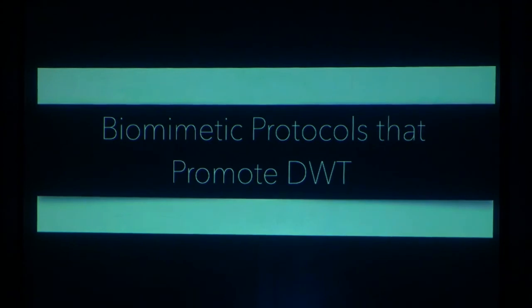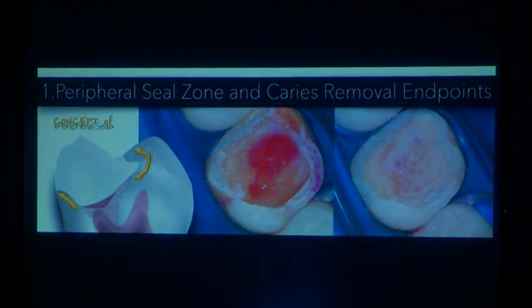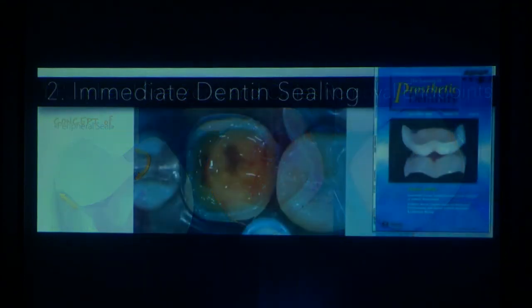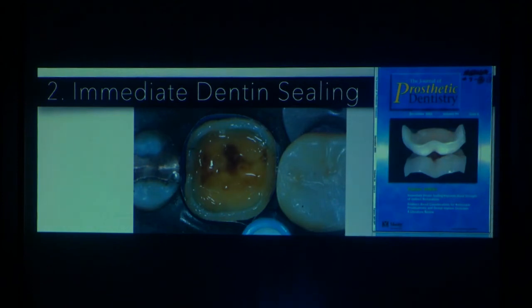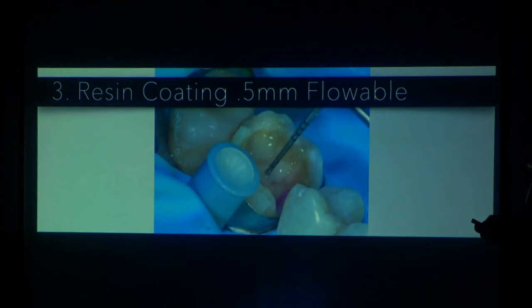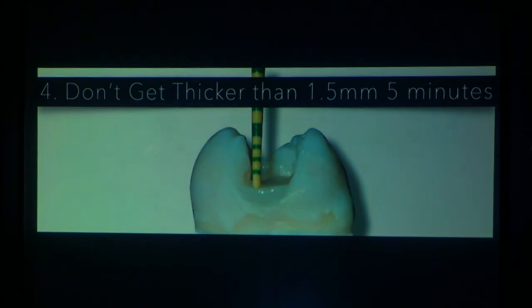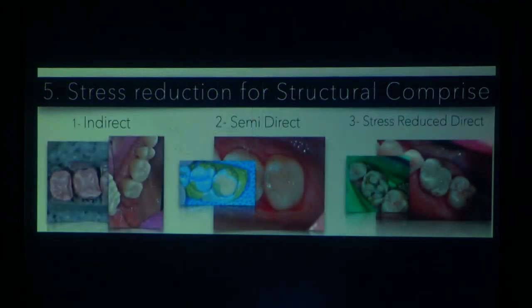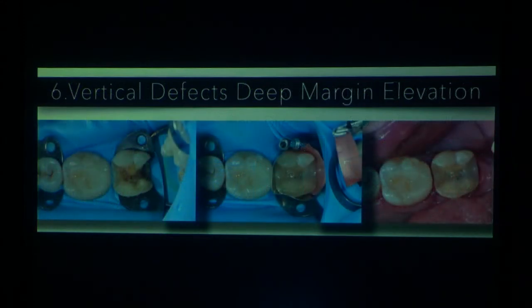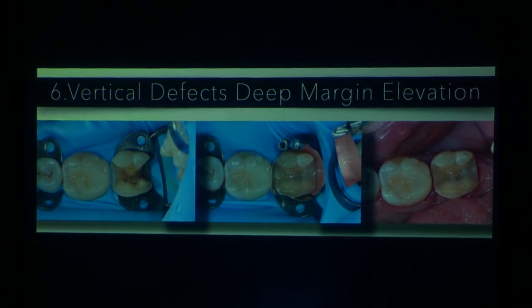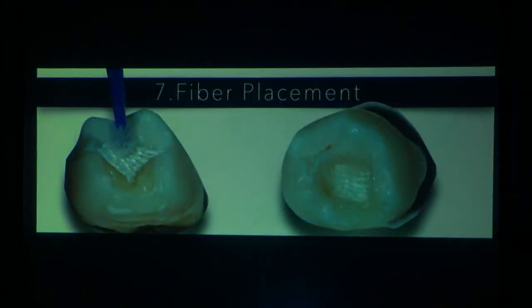All right. So the biomimetic protocols that promote decoupling with time, peripheral seal zone and caries removal endpoints give you the high bond strength. Immediate dentin sealing maximizes your bond strength. Resin coating gives you the fail-safe and takes time to place. Careful, thin increments take more time than bulk fill. Using an indirect restoration, a semi-direct restoration, stress relieves the enamel replacement, but it has to be used with immediate dentin sealing and resin coating. Vertical defects take a deep margin elevation as a separate procedure, and that also takes time. And fiber placement, again, takes time.